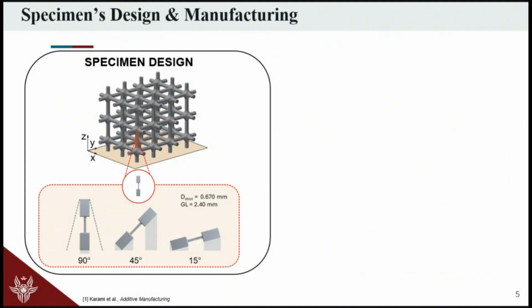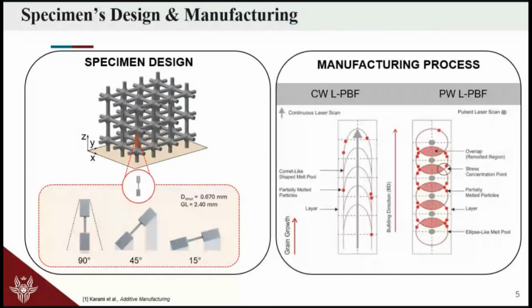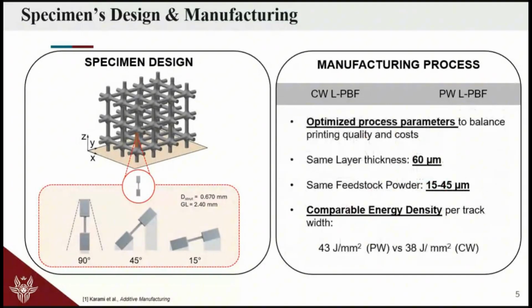To do this, we designed some specimens, which we call thin struts, which mimic the struts of a lattice, at three different building orientations, 90, 45, and 15, with respect to the job plate, with a nominal strut diameter of 670 micrometers and overall gauge length of 2.4 millimeters. These specimens have been printed according to the before-mentioned manufacturing processes, considering some optimized parameters in order to balance the printing quality and the cost.